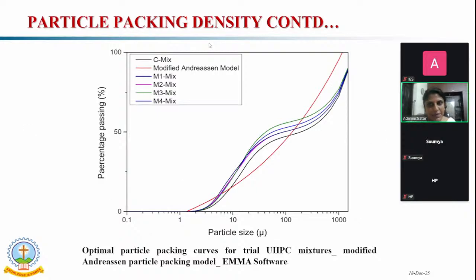This is one example of the EMMA software graph. By inputting the aggregate size and the effectiveness index, we will get the modified Andreasen model, shown in red color. That is the good particle packing curve. Then in that software I have inputted our mixes, the M1 mix, M2 mix, M3 mix, and M4 mix. If we add our mixes, then it will look like this.